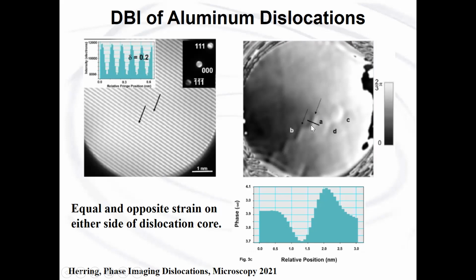This dislocation here goes from negative phase to positive phase, and then the one over here goes from positive to negative, so that forms a very nice network in here. And so we get to measure the phase, and the phase represents the strain around the dislocation.